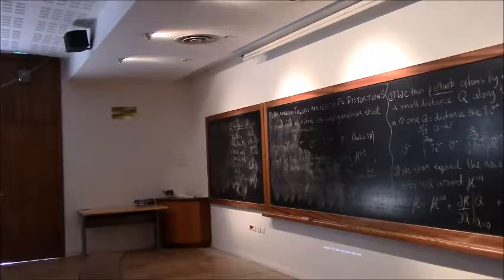Can you see if I write here, or is the table on the right? It's fine. So then I have two second order terms. One with the first order wave function and the second order perturbation to the Hamiltonian. This one's positive. Notice, positive is bad. If I want to become ferroelectric, positive is going to increase the energy, so this term is going to disfavor ferroelectricity. And then the second term, this one's negative, this is good. This one looks a bit more complicated, but it's the term that has the first order correction to the Hamiltonian combined with the first order correction to the wave functions. That's why it ends up looking a bit complicated.